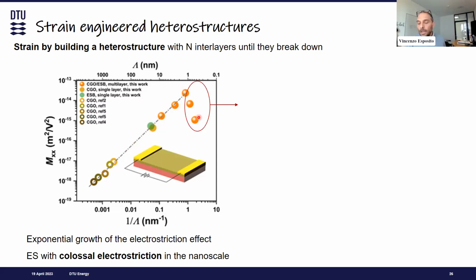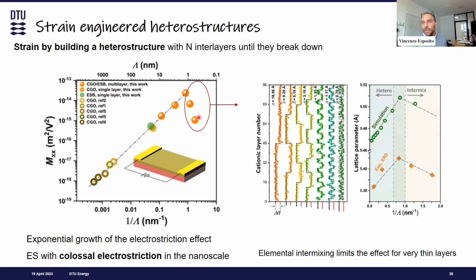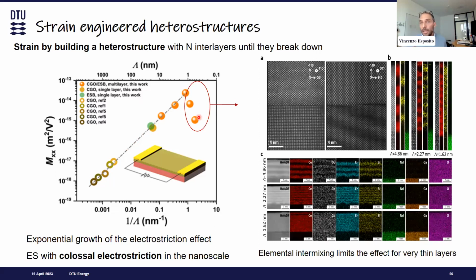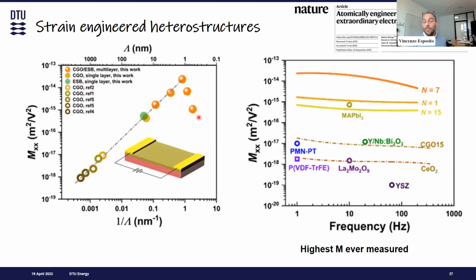This decline is actually due to the limit of this technology, which does not allow going for too many interfaces, since the layers get very thin, around 1 nanometer. Then we start having some intermixing of elements. This was also confirmed by chemical analysis, where we see that there is not much difference between the chemistry of one layer and another when we have too many interfaces and the films get too thin. So this picture gives you an idea of how many orders of magnitude in the electrostriction coefficient we can get using this strategy.